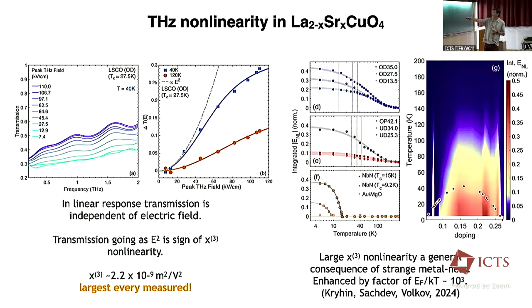So this is a plot, temperature versus doping. That's the Tc dome. Plotted on the board here is, again, the scale of the nonlinearity. Terahertz range nonlinearity should be enhanced where non-parabolicity is large, in a non-interacting system. So the question is, where is this coming from? Is it a band structure effect, a non-parabolicity, or is it coming from interactions? A place where the non-parabolicity should be largest is near the Lifshitz transition, which is about 0.2 in lanthanum strontium copper oxide.